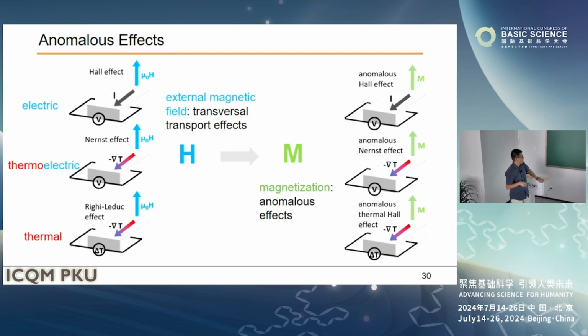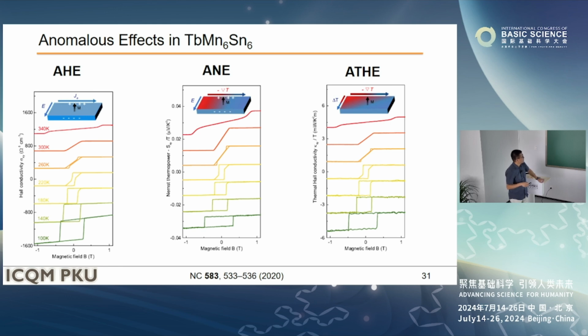For thermal Hall, you apply a temperature gradient, and you see a temperature gradient in the transverse direction. But if you measure those things in magnetic material, you see some anomalous counterpart. Those anomalous counterparts are strongly related to some topological properties. Actually, if you understand the distribution of Berry curvature, you can calculate the anomalous Hall effect and anomalous Nernst effect, theoretically, of course. So we also did those measurements, and we find a significant anomalous Nernst effect and anomalous thermal Hall effect. And those things can help us to understand the entropy and charge transport of a massive Dirac fermion.